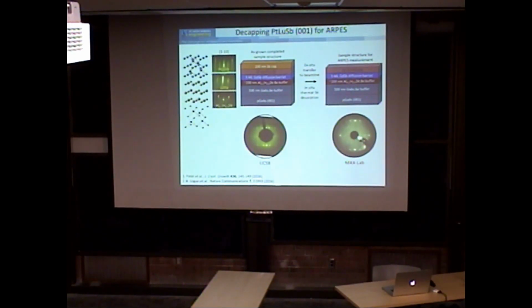So to do this, what we wanted to do was use an antimony cap. We can put antimony on top of this platinum lutetium antimony, heat it up and get the antimony to blow off and give us a clean surface.